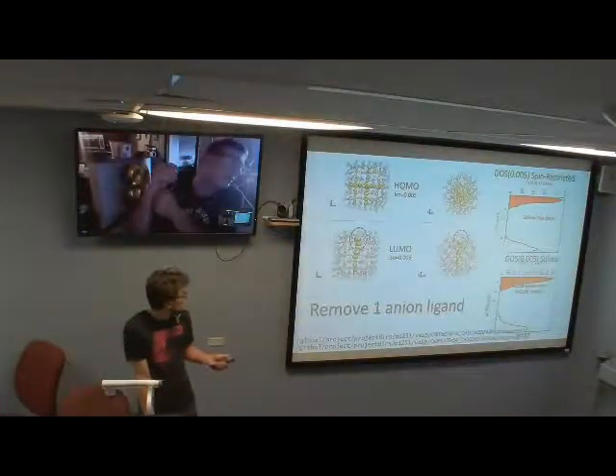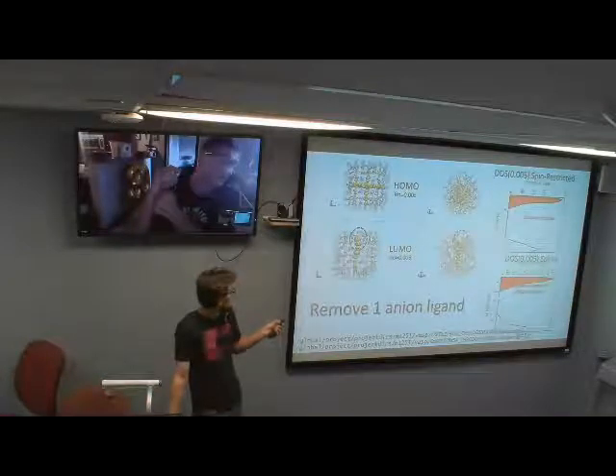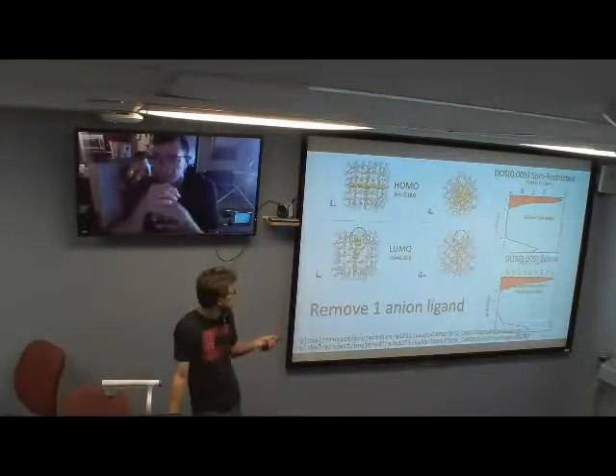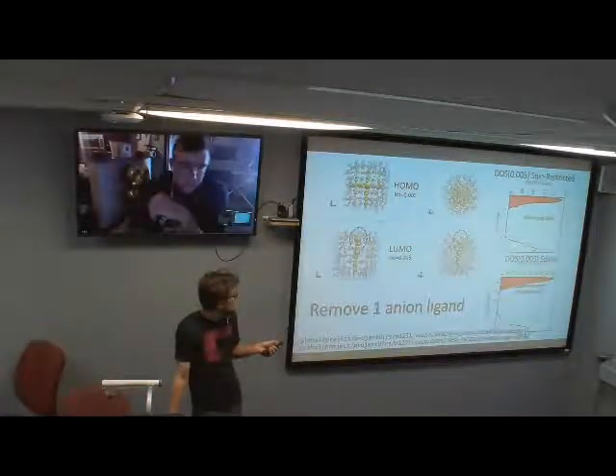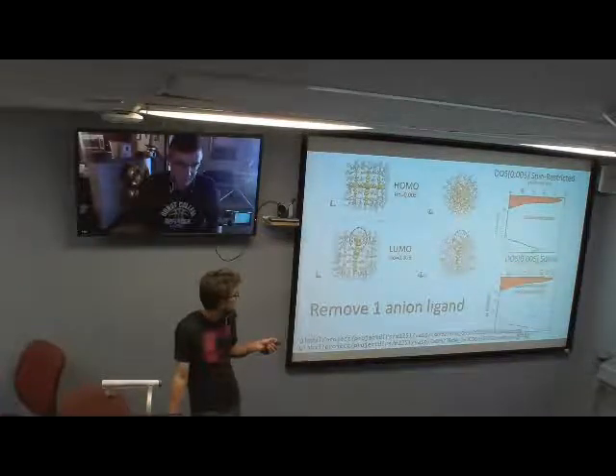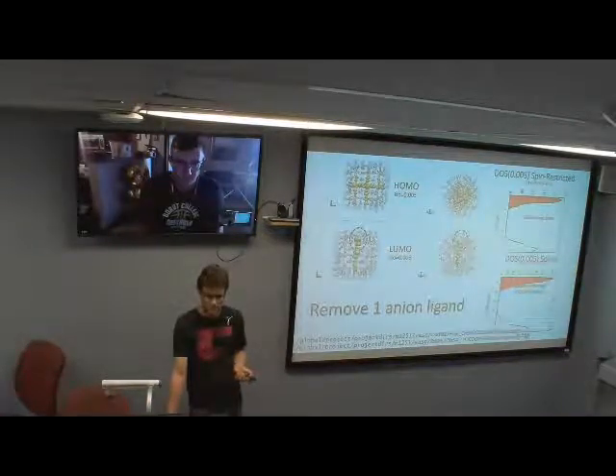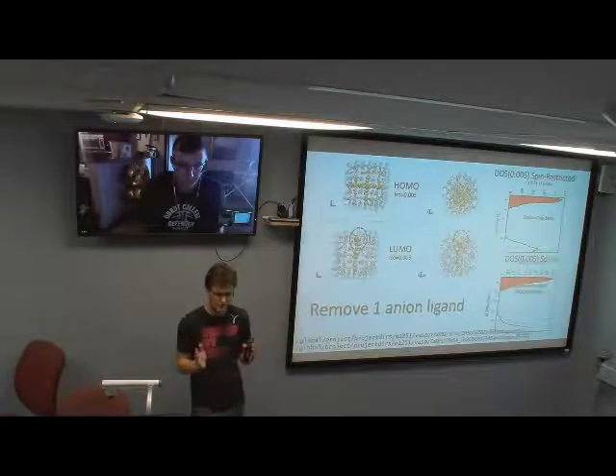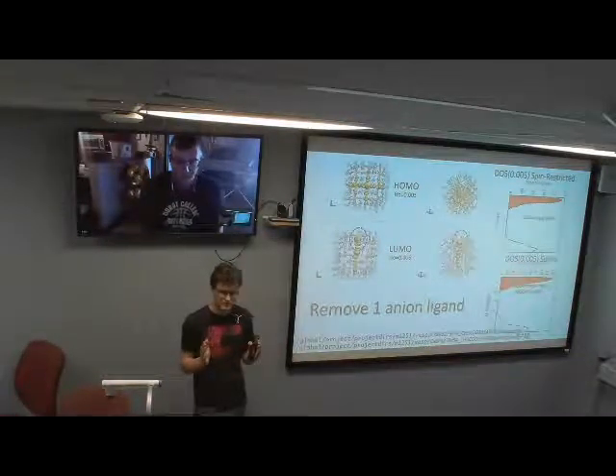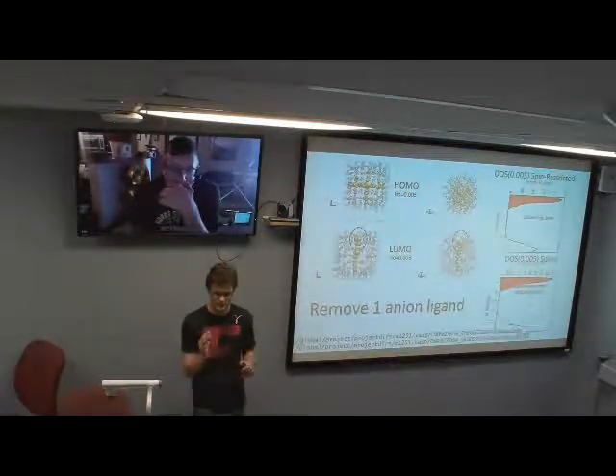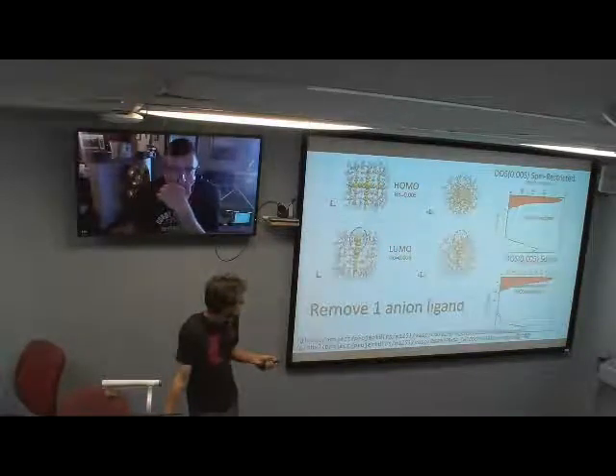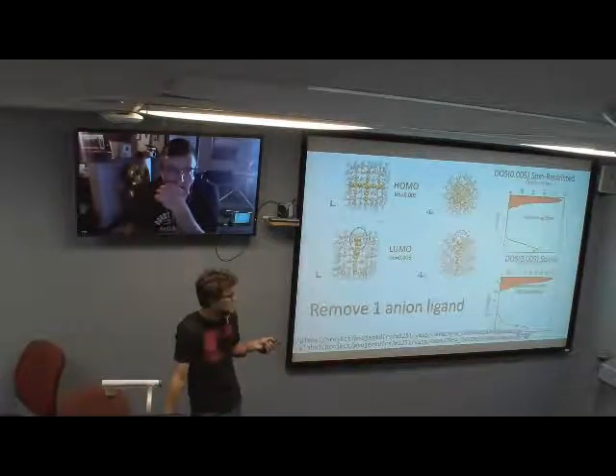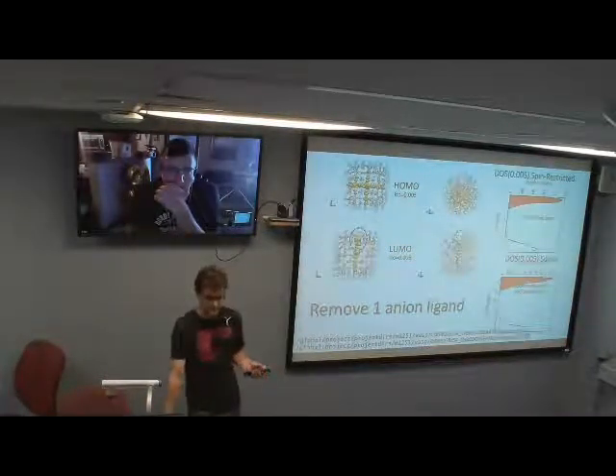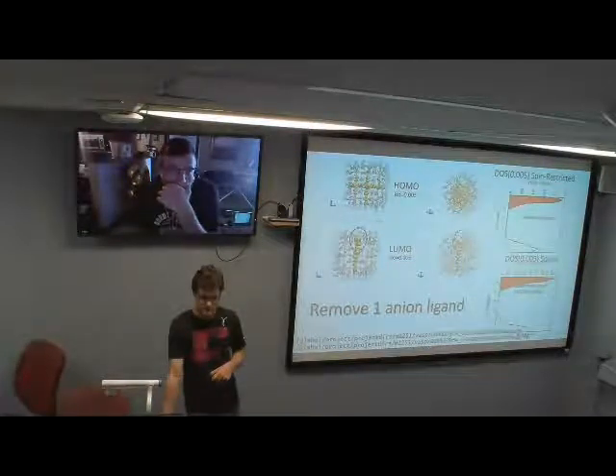So yes, when I remove the anion ligand to expose the lead surface, it seems there's a shallow trap state that pops out, but I would need a partial density of states to totally confirm that. It could just be Fermi leveling or redistribution of charges moving states around. And I was planning on doing absorption spectra for these two to see what the effect is on the spectra.